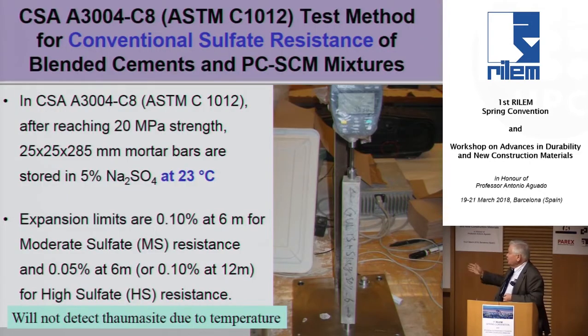And so our normal test method, which is the ASTM C1012 test, I know it's been criticized for maybe not representing all things, and I know Esperanza's been involved with the RILEM committee on developing a better test method for the European experience or world experience. But we've had this test method since around 1981. You cast mortar bars, you wait till they get to 20 megapascal strength, you put them in a pretty strong sulfate solution, and you immerse them and measure the expansion. But at room temperature, you're not going to pick up Thaumasite. It will typically form ettringite and cause that swelling.